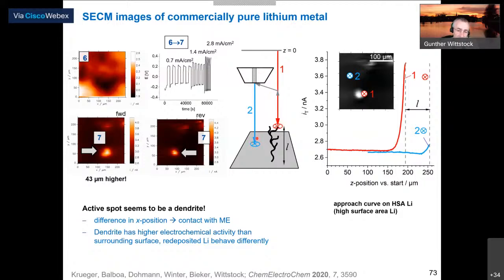And we see, first of all, a height difference, which tells us that something like a high surface area lithium was formed, because there is a different point at which we have to stop the approach. And secondly, if we compare the approach curves, we see that the current rises steeply to much higher values than in the case of the original surface. So we see that not only the height has changed, but also the reactivity.